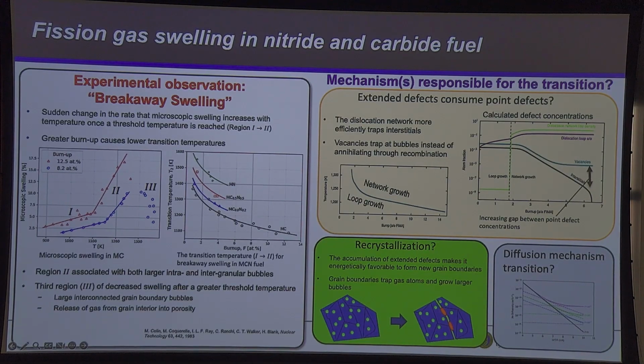Metal fuels are really good for thermal conductivity, but they swell a lot, so they change the geometrical form a lot. That can be engineered around. Nitrides don't swell as much, at least if you operate them under the right conditions. So this exercise goes through defining the same kind of models that I described for UO2. And the problem we want to solve is, at what temperature and radiation condition do you need to keep this fuel to avoid swelling increasing almost exponentially? So that's expressed by this point here.